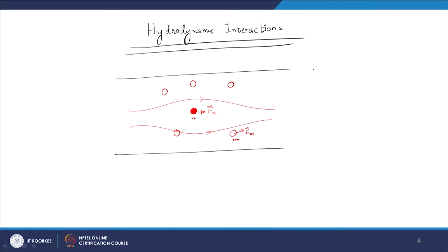It is more pronounced if the size of the bead is larger. It is less pronounced when the size is smaller. In the limit when we have a very dilute solution and sizes are smaller, we can ignore this effect, but it turns out that that limit is seldom reached. In most systems, the effect of hydrodynamic interactions is quite significant and must be included for a proper description of the system. So, now in general, if I am looking at the velocity